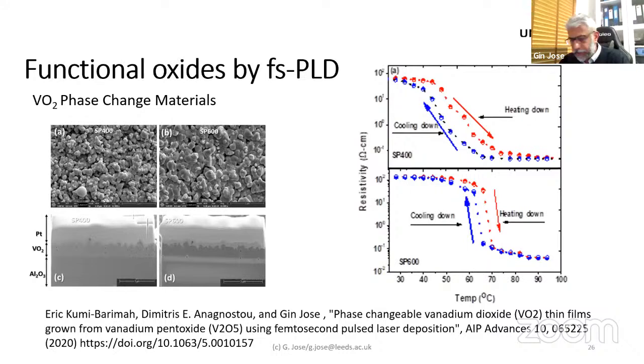Another thing we use it for is deposition. It's basically different from the doping process. It's a simple deposition process. You can deposit, say, oxide materials like vanadium oxide, which is an interesting phase change material, which means that it can change its crystalline phase with temperature or by electrical excitation. This shows its phase change properties, its resistivity change with temperature. It has also been published recently.